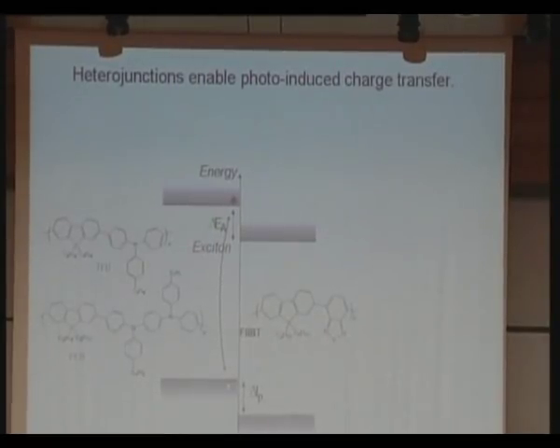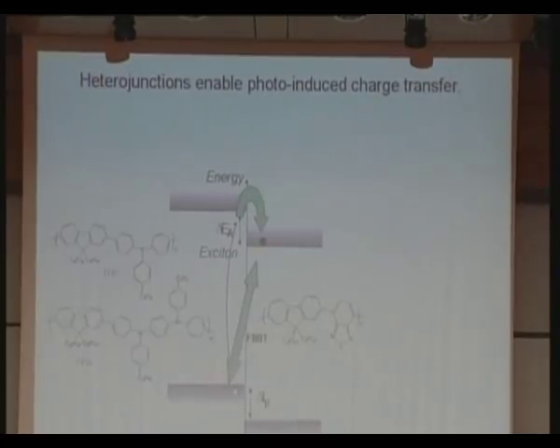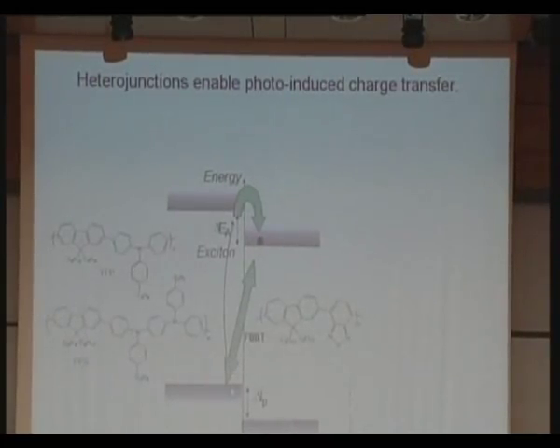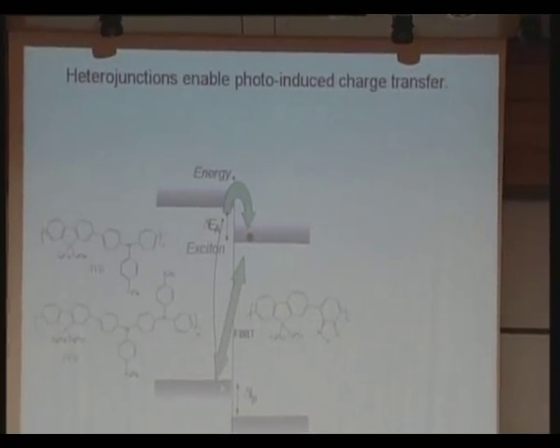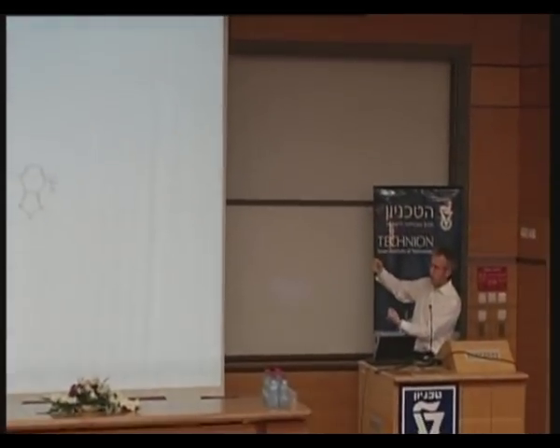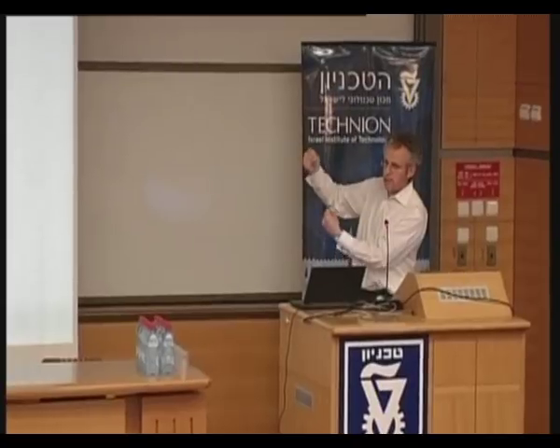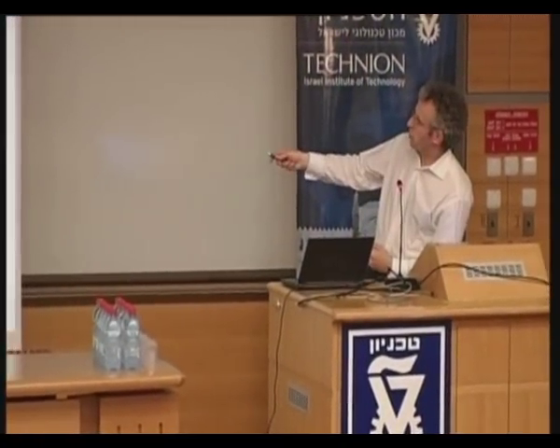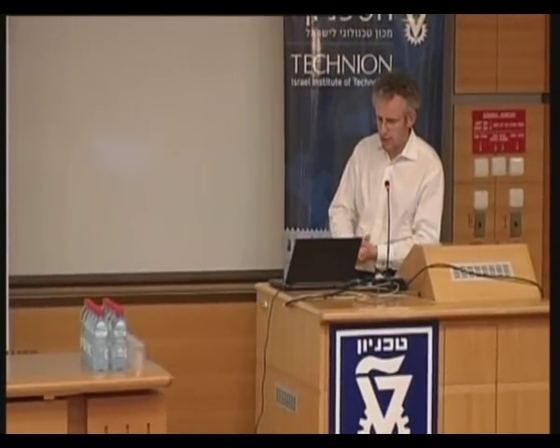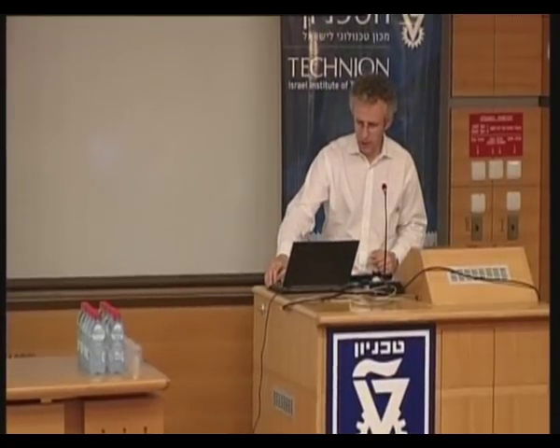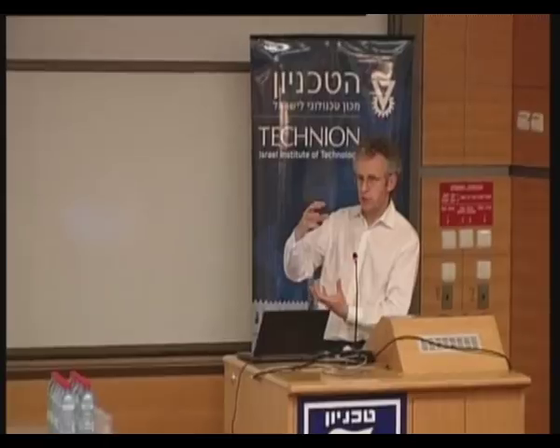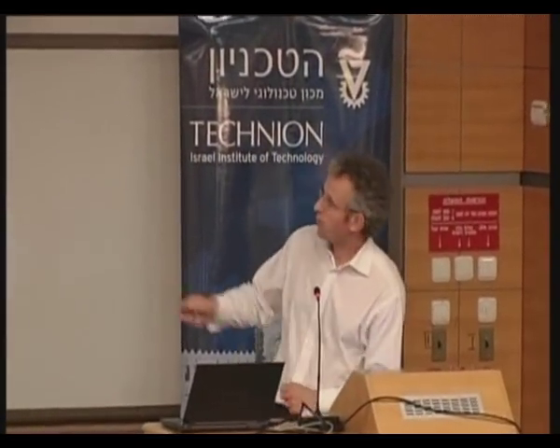But what's interesting about this combination is that when we photoexcite, we get something which appears to be charge transfer across the heterojunction, but there things get stuck. The electron and the hole are definitely not sitting on the same polymer chain, but they're definitely still in a bound state. And what we've got is an excitation across the heterojunction, which in chemical language is probably called an exciplex. And the characteristics of it are that it's a lower energy state than if we just got the exciton on one chain or the other. So there's a redshift. We've also got an optical transition, which is across from one molecule or one polymer chain to another polymer chain across the heterojunction. And the matrix element for that optical transition is much weaker than if the transition were just on one molecule.